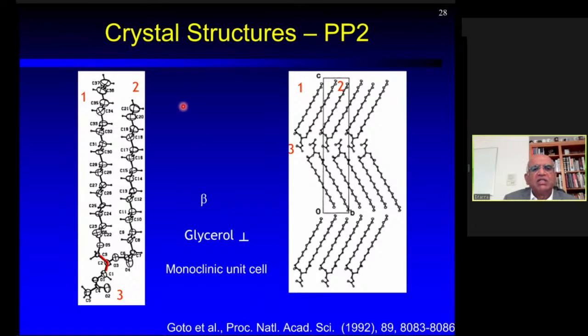Here, what I'm showing is the mixed acid triacylglycerol PP2. The molecular orientation at the atomic level structure is shown on the left with the 1,2 dipalmityl chains and the short 3 acetyl chain. And the same PP2 projected along the a-axis is shown here, the monoclinic unit cell having two molecules present in the unit cell, where the 3 acyl chains are segregated and form a middle layer interposed by 2 layers of palmityl chains. That gives the glycerol, once again, a perpendicular orientation.